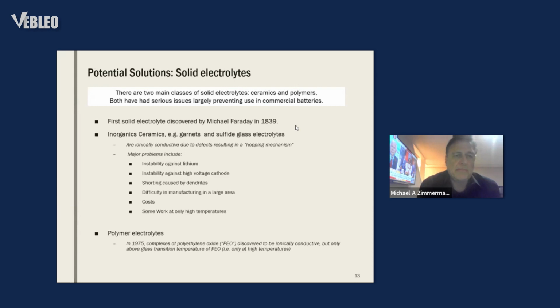But again, as I mentioned, there are two classes. There's inorganic ceramics, and that's dominated by two different classes within that. One is garnets, or LLZO, and the other is a sulfide glass electrolyte, and actually Toyota is one of the major development companies working towards solid state batteries using sulfide glass. The mechanism of ionic transport is basically hopping due to defects in these materials. Until recently, these only worked at very high temperatures, but there have been some innovations recently which have allowed them to go to lower temperatures.